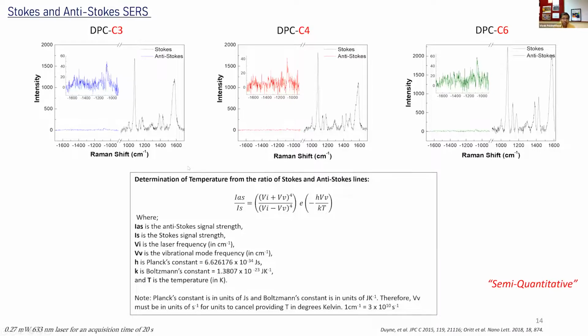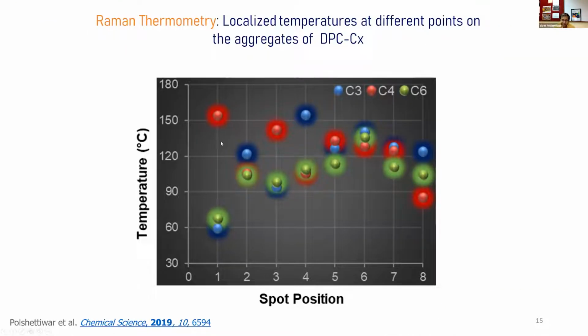So using this Raman thermometry, we found that the surface temperature of these nanoparticles can go up to 150 degrees Celsius. Again, there is heterogeneity because materials are heterogeneous, but you are in the range of 120 to 150 if I look at the C4 material. Again, these numbers can be different if I change the light intensity or the light wavelength. These numbers can even be more. Theory says it can go up to 400 degrees Celsius.